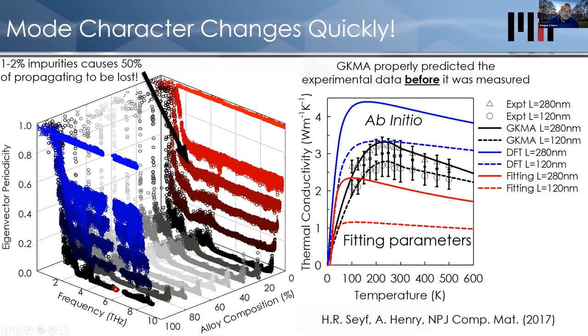spot on. What this plot on the left is showing you is a measure of how many of the modes are actually propagating, or look like plane waves, as you change the alloy composition. Initially, when it's a pure crystal on this side of the plot, all the modes are plane wave modes. They are all 100% propagating. This is the periodicity in the eigenvectors. They're fully periodic. But as soon as you break the symmetry and start adding a few alloying elements, this drops and you get almost no periodicity once you make it an alloy. So this, again, has helped us realize we need a different physical picture.